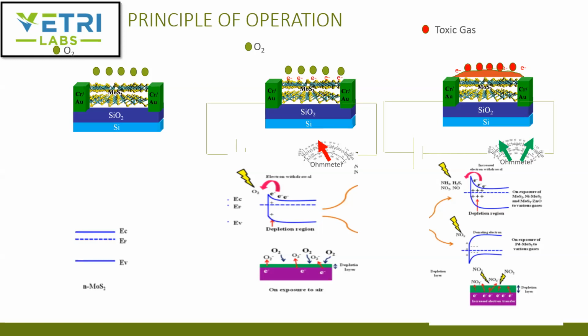And if the toxic gas is reducing, that should replenish electrons in the conduction band, which will then reduce the resistance and increase the current. So it depends on if it is an oxidizing environment or a reducing environment.